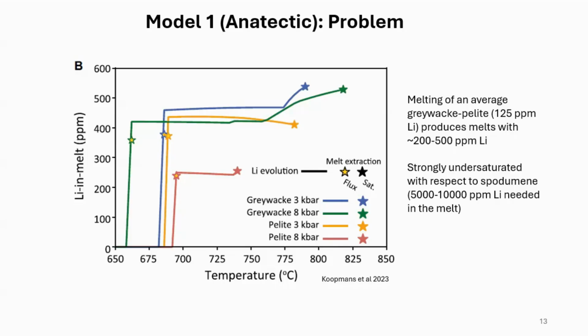So we believe that it's not a single stage process. It's a matter of melting a source. The source doesn't have to be particularly enriched. Melting that source, crystallizing that granite, a new heat pulse comes in, melt that granite, it moves on, and it crystallizes either directly as the lithium pegmatite, or there's another remelting. We have evidence in the geological record that we have periods of heat that are 20 to 40 million years in length at the end of orogenic cycles.